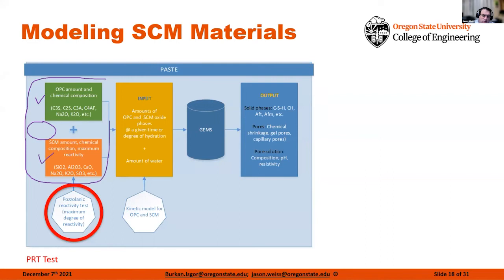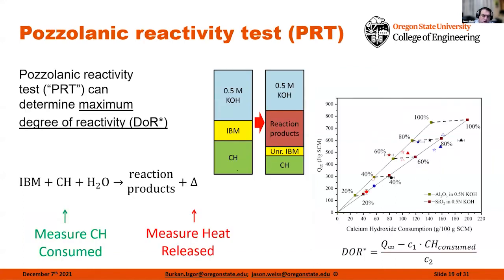Now, one of the things that we've tried to demonstrate over the last several years is we need a measure to say how reactive is this SCM that you're bringing in. And we're actually using a test that's been developed, a very simple test called the pozzolanic reactivity test. The pozzolanic reactivity test is exactly what the test sounds like. It's measuring how reactive this SCM is. We then add in some kinetics and we're able to go through and produce this type of thermodynamic model that we're talking about.